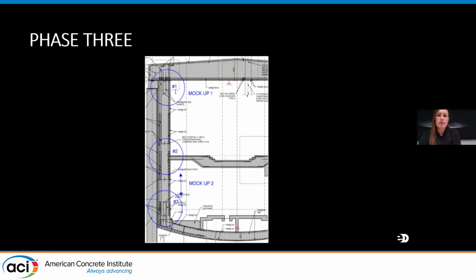So this is very promising, suggesting that a high volume slag shotcrete mix will work if the contractor can properly shoot it. So we needed to test that. The purpose of conducting a full scale mock-up was to ensure that the mix and shooting methods can provide full encapsulation of the heavily congested rebar details, monitor the heat of hydration, and as well we wanted to use this to pre-qualify the nozzlemen and the shotcrete contractors.